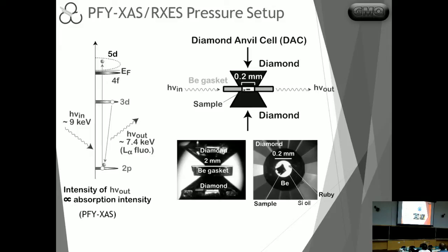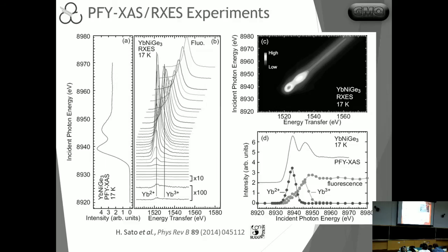In the case of the PFY, you're going to directly look at the intensity of the energy coming out. And this energy that's coming out is usually due to the fact that when you excite a 2p electron up, typically a 3d electron is going to jump down to 2p. So basically what you did here is transfer a certain amount of energy from the in to the out of your system. And in this case, you can then do the temperature and the pressure dependence on it. So here's an example of what it looks like when you look at the partial fluorescence yield. It does look a lot like the absorption spectra, just because it's basically directly proportional, what comes in and what comes out.